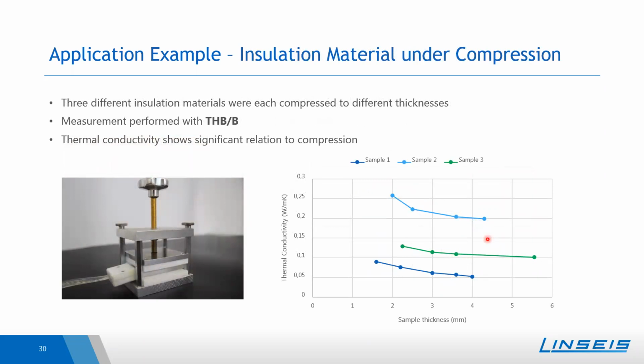And as already mentioned before, I want to show you also an application example of some soft insulation material under different compressions. But here we did not control the pressure force itself, but we adjusted the sample thickness using such a manual press so that we could have the material in different thicknesses. For this measurement, also a THB sensor was used, the smaller version, which is called in our company THB-B, which describes the smaller THB sensor.